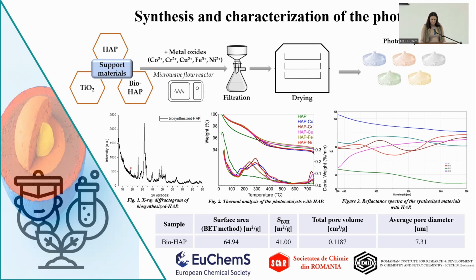studies. In figure 1, we presented the X-ray diffractogram of the biosynthesized hydroxyapatite. We can see that all the specific peaks which correspond to the general structure of hydroxyapatite are present, and also there is one other peak at 18.05 degrees, which corresponds to a disodium phosphate phase. This phenomenon is also explained by the usage of sodium hydroxide to maintain one of the important parameters in the synthesis of hydroxyapatite, namely the highly basic pH of the solution.